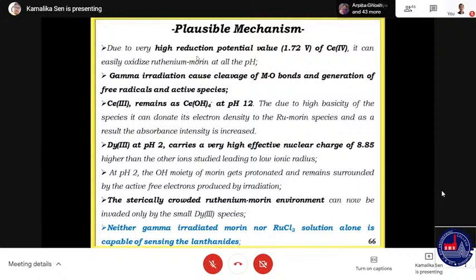So due to the very high reduction potential of cerium, 1.72 volt, it can easily oxidize ruthenium morin at all the pH. Gamma irradiation causes cleavage of the M-O bond and generation of free radicals and active species. Cerium 3 remains as the hydroxylated cerium species at pH 12, due to high basicity of the species. It can donate its electron density to the ruthenium morin species, and as a result, the absorbance intensity increases. For dysprosium at pH 2, it carries a very high effective nuclear charge of 8.85, which is higher than the other ions. And at pH 2, the OH moiety of morin gets protonated and remains surrounded by the active free electrons. The sterically crowded ruthenium morin environment can now be invaded only by the small, highly charged dysprosium 3 species, and hence can be sensed.